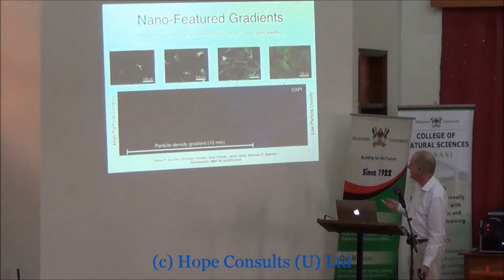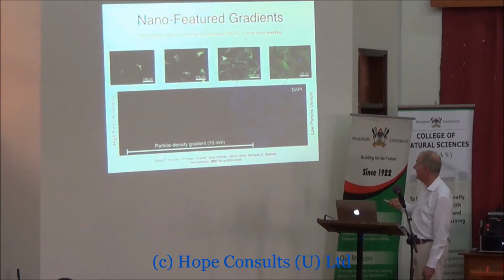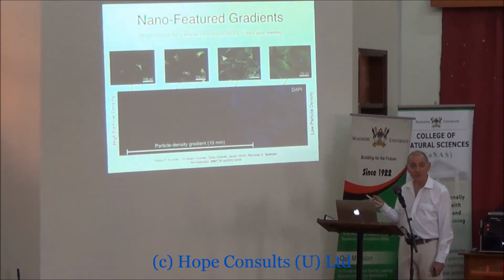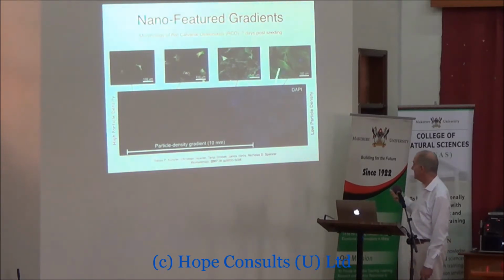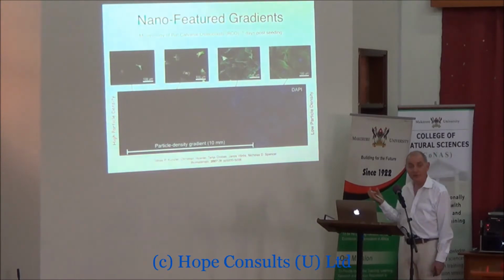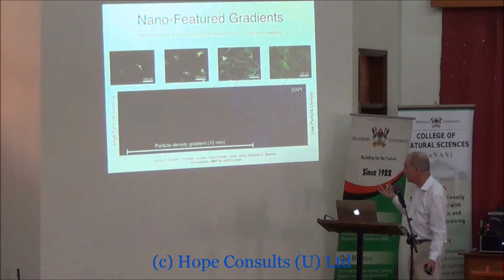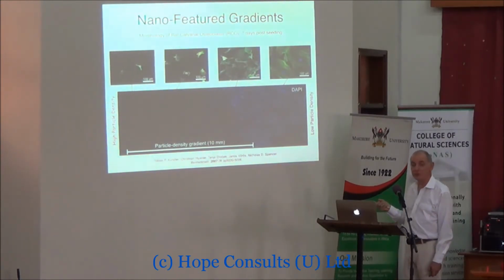Now this shows what happens when you expose them to the bone cells. Again, we have an enormous difference from one end to the other. But the surprising thing is it's the opposite difference from what we saw on the micrometer scale. At the flat end, we have cells. We have about the same number of cells we have on the flat end of the microscale gradient, which is good because they're both flat. But as we go to more and more nanoparticles, we actually see fewer and fewer cells. So on the nanometer scale, the more nanoparticles you have on there, the fewer cells want to stick. And when you have the highest density, you really have hardly any cells sticking at all.